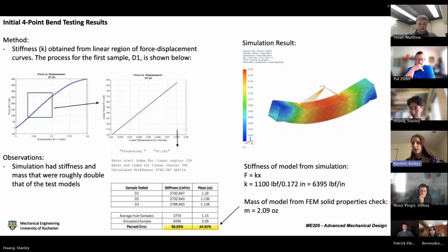First, we started out with the 7-inch samples, and as you can see, we got a pretty high percent error between the tested and the simulated results. It was like a 57% error between the two for the stiffness, and pretty much the same for the mass. So we saw that they were doubled, and we had to narrow down on why the stiffness and the mass were doubled in the simulation when compared to the tested results. If you could go to the next slide.